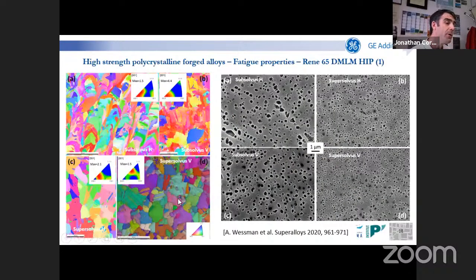So we have been working in collaboration with GE Additive in the US and with a colleague from the University of Arizona, working on Rene 65. So an alloy very difficult to print with a very high volume fraction of gamma prime precipitates. So here you can have an idea of the precipitation state. So you have typically 40–45% volume fraction of gamma prime precipitate. A little bit of borides and carbides also.